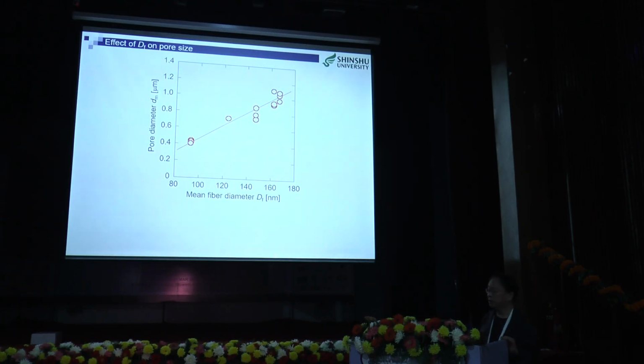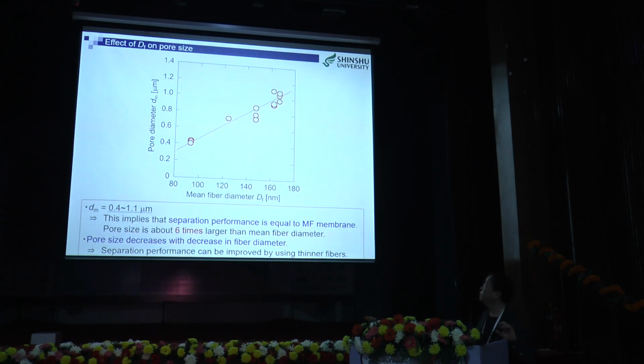First result. This figure shows the pore diameter against the mean fiber diameter. As shown in this figure, the pore diameter is in the range of 0.4 to 1.1 micrometer. This implies that separation performance is equal to microfiltration membrane. In addition, pore size is about 6 times larger than mean fiber diameter. Thus, pore size decreases with decrease in fiber diameter. This implies the separation performance can be improved by using thinner fibers.